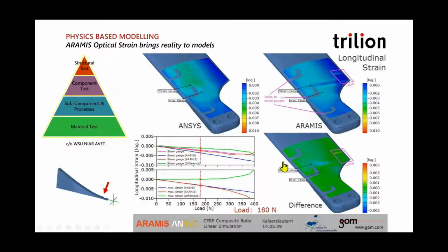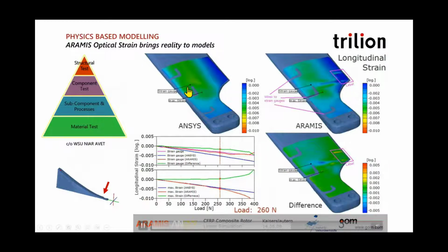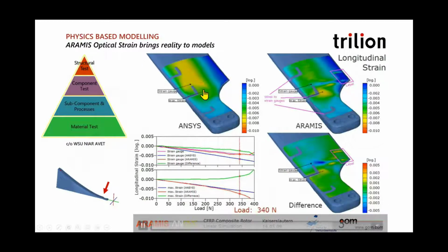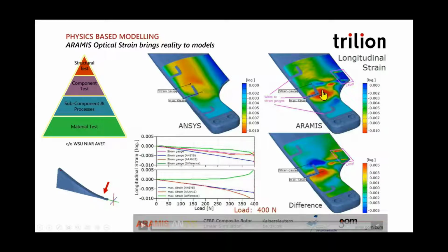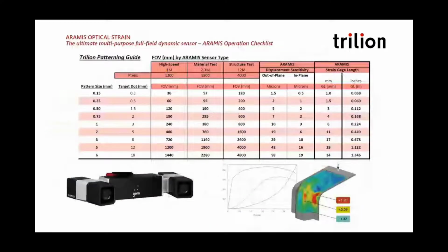When you get into real structural testing, normally you put a strain gauge down based on what the model says, but many times the model is very different than what's reality. In this specific case, there was a core splice in this blade that was not in the model, and so the strain fields are completely different, and the results are completely different. Only full field data can give you these results.